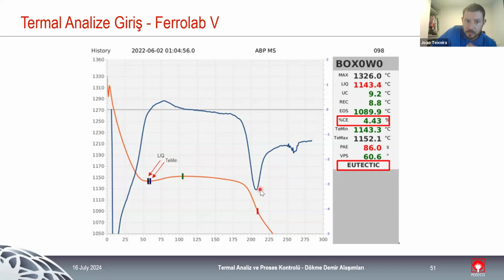So to improve the VPS with gray cast iron, I will probably try either an inoculant with strontium or an inoculant with lanthanum, for example, because lanthanum can increase a lot the nucleation spots for the gray cast iron, and we can have more expansion uniformly distributed in the cast. So using one of these, we can probably reduce a little bit the VPS and reduce the problems that we could have during this stage. So again, the problems are porosity and micro shrinkage, and if the VPS is really, really high, we can have some micro shrinkage as well.